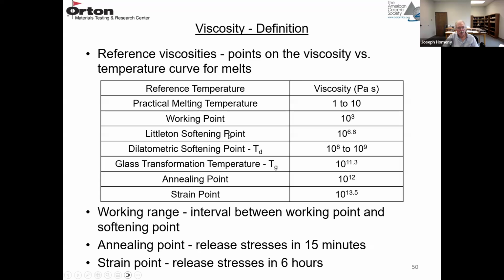The Littleton softening point is 10 to the 6.6. The Littleton softening point is defined by an ASTM standard. It's based on a fiber elongation experiment. So you have a fiber, and when it starts elongating at a certain rate, that corresponds to this viscosity, 10 to the 6.6.